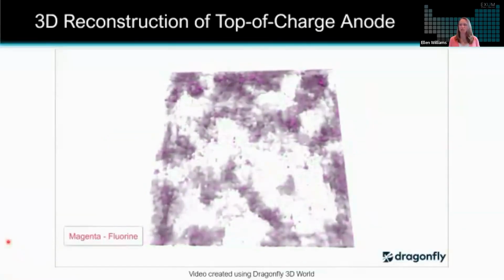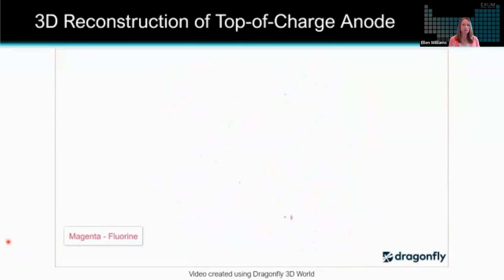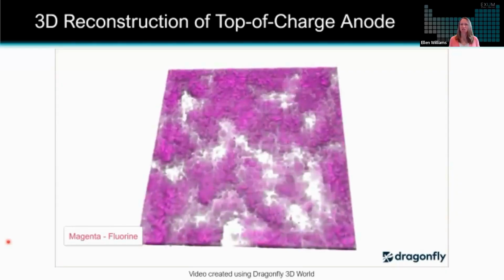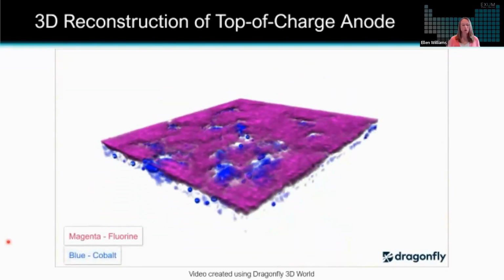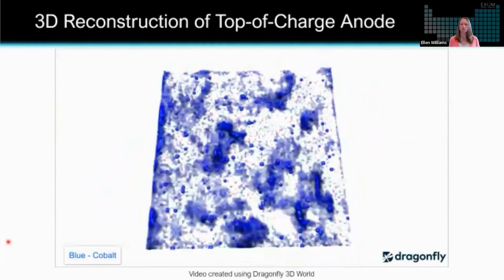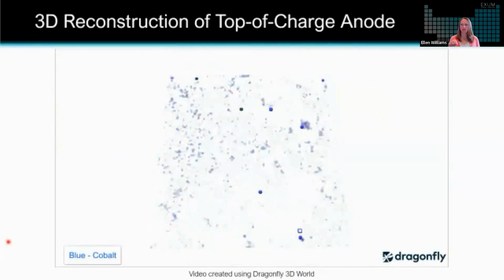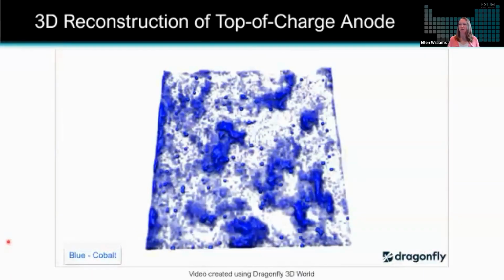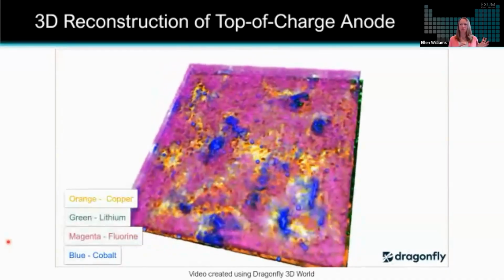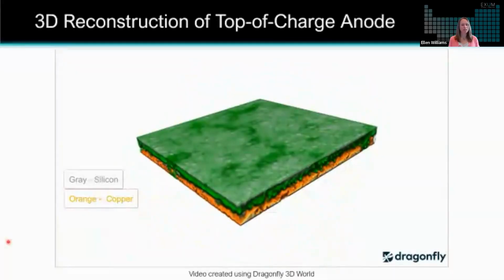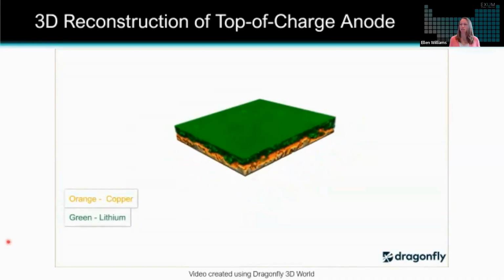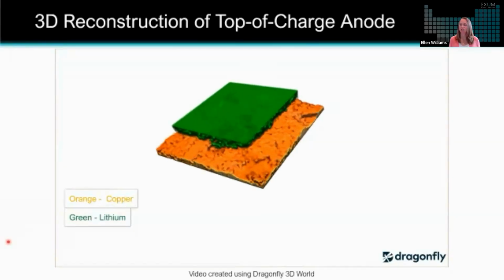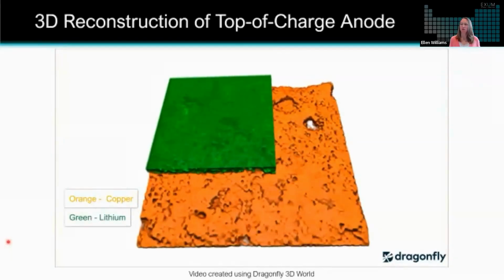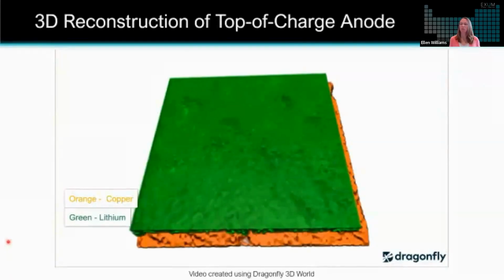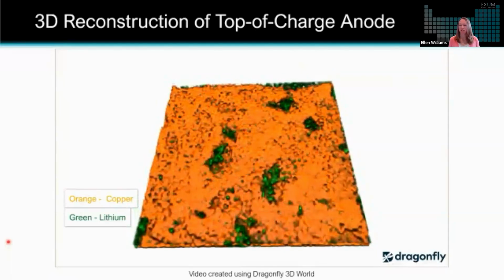So fluorine being a major constituent of the electrolyte, this may indicate that we're getting some SEI, solid electrolyte interface layer formation. And what was a surprise here is the trace amounts of cobalt that were identified. So you can see these discrete areas of cobalt. And if this analysis had been done on the raw material, we could have determined, was this cobalt an impurity that was in the silicon anode before it was turned into a slurry and distributed on the copper current collector? Or did this occur from a migration? Was this cobalt migrating from the cathode during the cycling process?